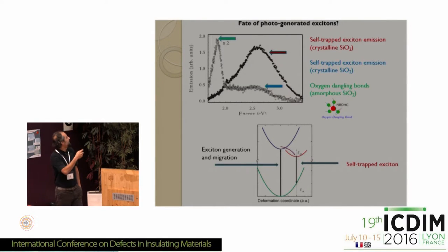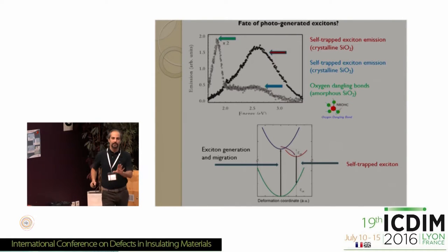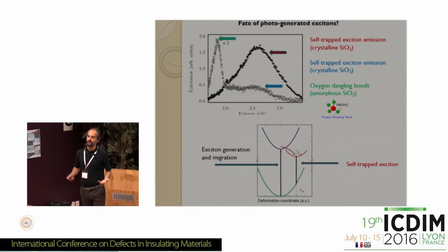So these results tell us that excitons, after they are generated, can eventually end up doing two things. They either get trapped, form self-trapped excitons, which are capable of emitting photoluminescence here, or excitons can decay non-radiatively in another way that leads to the formation of point defects. So this is a direct evidence of the process by which excitons form point defects in SiO2.